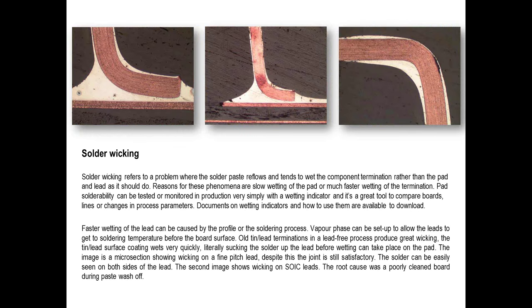With vapor phase, if you don't balance the preheat and also the reflow, again, the solder paste can tend to wet to one surface more than another. Now, this will normally happen on J-lead or gullwing terminations. It doesn't really affect other parts to the same degree because you've got a long pin taking the solder away from the joint interface, which is what you want. And theoretically, as you reduce the volume of solder, you reduce the long-term reliability of the printed circuit board